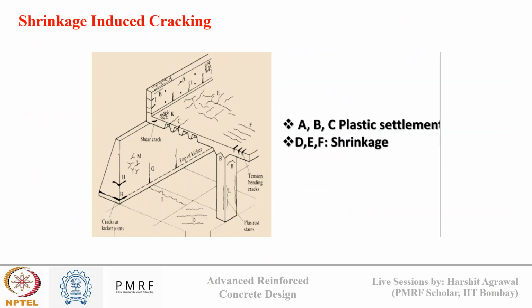And in this image, you can see different ways in which shrinkage cracks are generated. This is a typical building plan, and there are different types of cracking present in this image. A, B, C are due to settlement. However, D, E, and F, you can see here, here, and here, these longitudinal and transverse cracks are due to shrinkage, and you can see they are all at the slab surface, where a higher surface area is exposed to the environment. Such cracks can appear due to shrinkage in a structure if it is not cured properly, or if it is not taken care of properly during the initial strength gain phase.